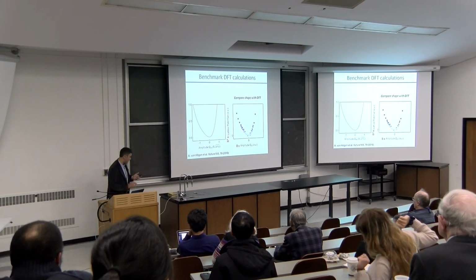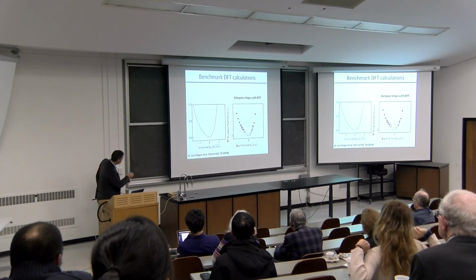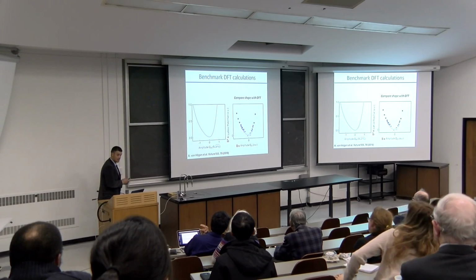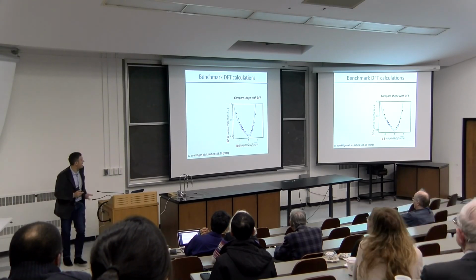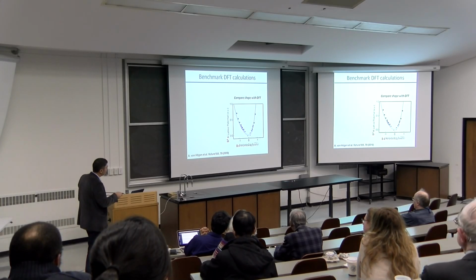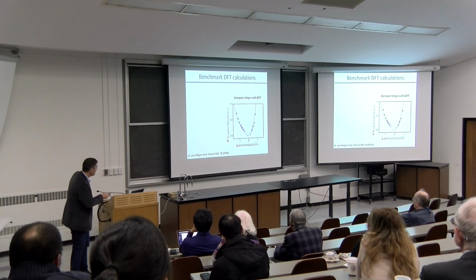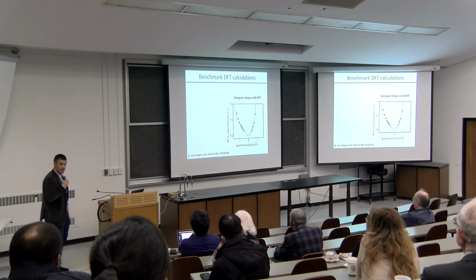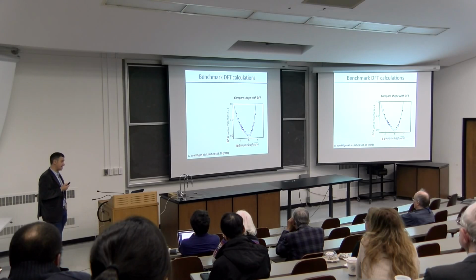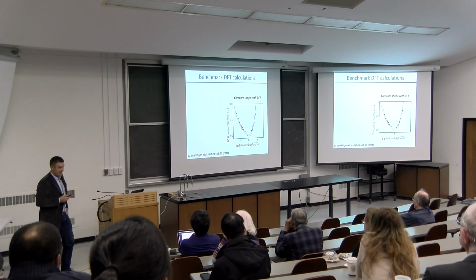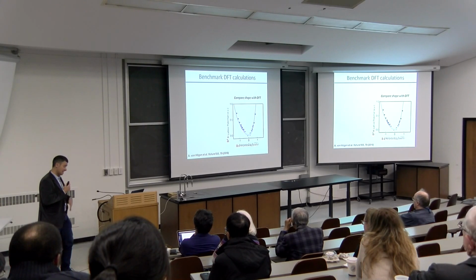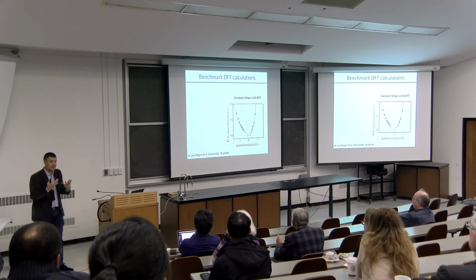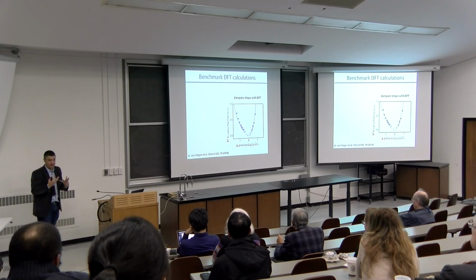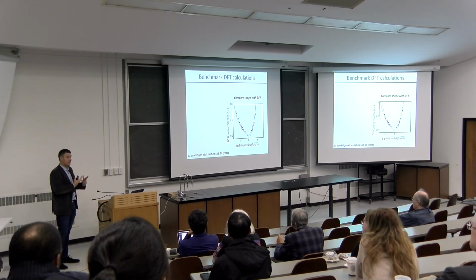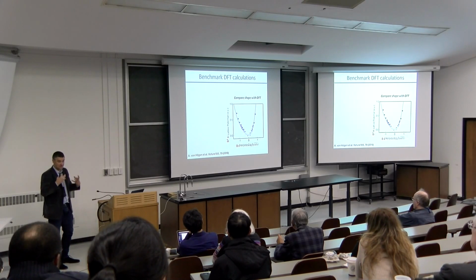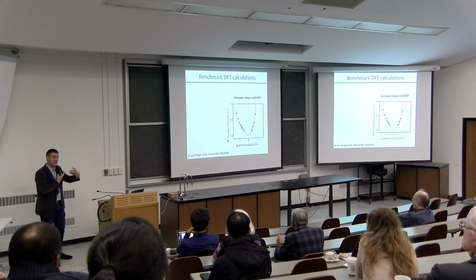So now this is lithium niobate, which is not anything to write home about. So you can take a DFT expert that calculates this, and you can now go back to him or to her and say, look, you're doing a good job in the first, second, and third expansion term, but your fifth and sixth is really not that good. And what's quite interesting at some level, at least to write a paper, is that because the interatomic potential is a 3n minus 3 dimensional space, and I have 3n minus 3 phonons, if I build 3n minus 3 lasers and I do the experiment so many times, I can map the interatomic potential in an interesting way.